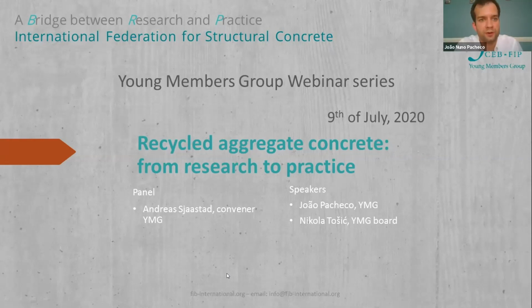And a question from Flood about tensile cracks being smaller. Yes, this happens for a main reason. Since the tensile strength will be smaller, you will reach the strength necessary for cracking faster. So you'll have more cracks and they will be smaller for the same displacement or strain. And about reinforcement anchoring lengths, it will tend to increase because of the differences in model uncertainty, but that is under calibration right now.